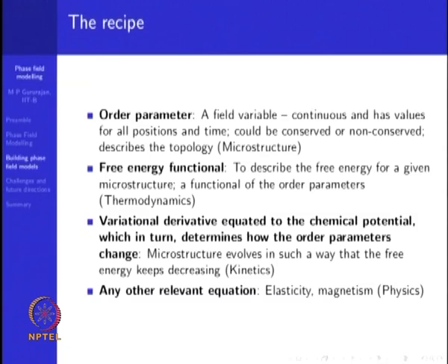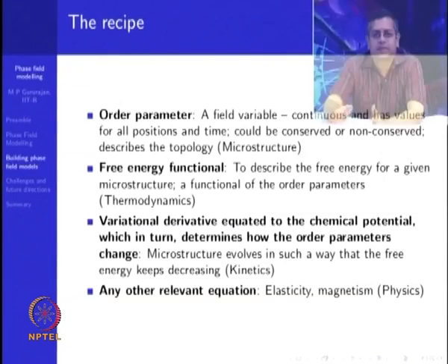The purpose of this order parameter description is to describe the geometry of the microstructure. Once you have defined the geometry, for the given geometry you have to describe the thermodynamics. That is done by giving the free energy, or entropy in some cases, but we have been sticking to the free energy functional because in solid phase transformations, most of the time we are assuming that temperature is a constant.